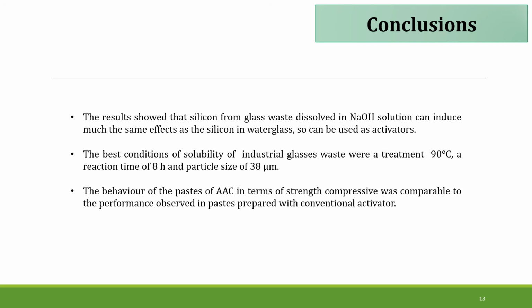The best conditions of solubility of industrial glass waste were a treatment at 90 degrees Celsius, a reaction time of 8 hours, and a particle size of 38 microns. The behavior of the pastes of alkali-activated cement in terms of compressive strength was comparable to the performance observed in pastes prepared with conventional activator.